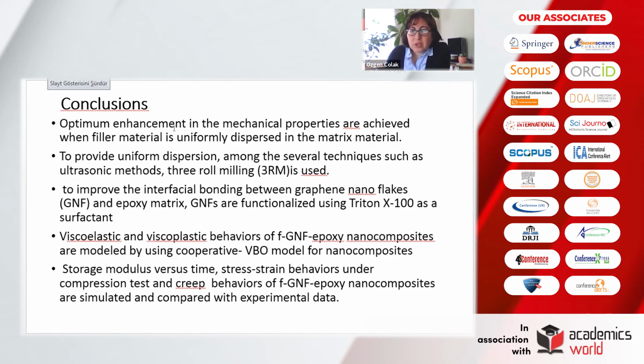If we conclude, optimum enhancement in the mechanical properties is achieved when the filler material is uniformly dispersed in the matrix material. As I mentioned, an important thing in nanocomposite manufacturing is uniform dispersion of the nanofiller. So when a 3-roll mill is used, good dispersion is obtained. Even though I haven't presented it here, we had some SEM images which show that the distribution of the graphene is quite good.